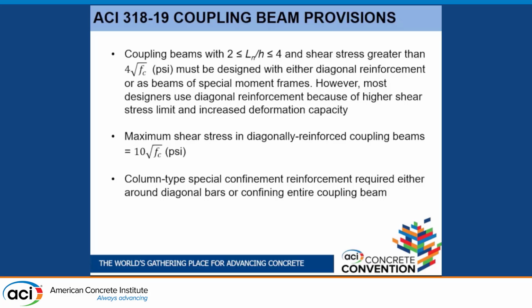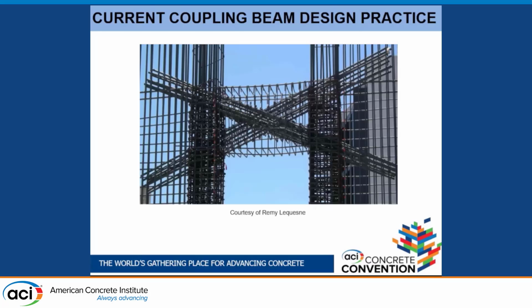As mentioned, we need special confinement reinforcement, similar to the confinement reinforcement needed for potential yielding regions in a column of a special moment frame. That leads, in combination with the diagonal bars, to severe reinforcement congestion as shown in this photo. You can get very large diameter diagonal bars required to resist the entire shear. Also, the larger the aspect ratio, the shallower the diagonal bars are, and the less efficient they are, so you end up with fairly large areas of diagonal reinforcement.